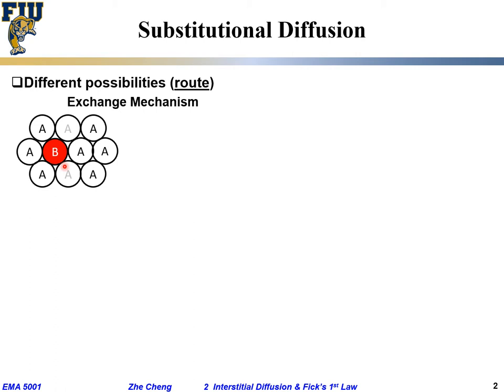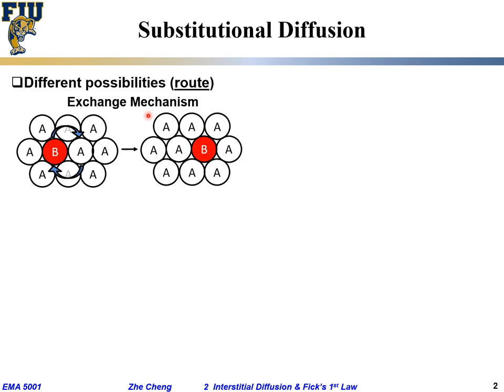Of course, one possibility would be A and B directly exchanging their position, right? B moves directly, exchanging position with a neighboring A. This is the so-called exchange mechanism. But as you can imagine, after it exchanges, B moves one spot to a neighboring spot. This process will have to overcome a high energy barrier, because the atoms are packed pretty close, pretty dense. It would be difficult. You have to push around, like in a very crowded bus. It's difficult for one person to move because they really have to push around, versus a weekend bus.